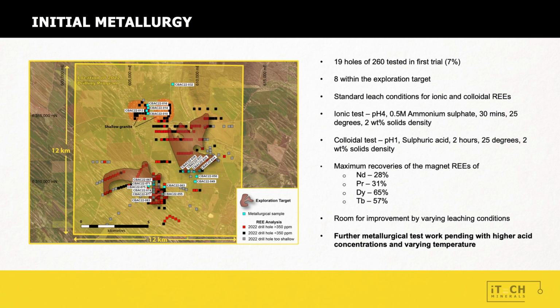Now what we'd really like to do is get those recoveries up to well above 50, to the 60-70% sort of recovery areas. So what we've gone and done is sent those samples back, and our aim is to do another round of metallurgical testing where we're going to keep adding higher increments of acid until we can get the bulk of those rare earth elements into solution. So that test work will be available. The results of that test work are aimed to be available by the end of November.